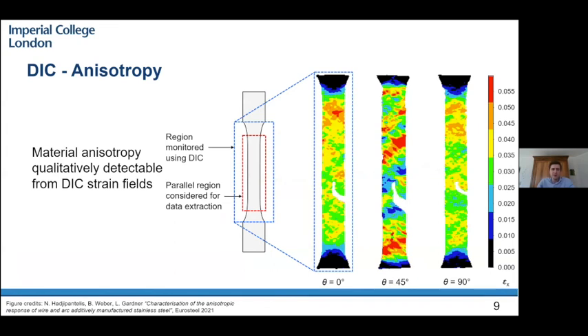From the raw data from these tests, which you can see, for example, on the right-hand side for longitudinal strain graphs, we can also already get a qualitative assessment of the material behavior. And you can clearly see that the strain plots are not the same for the 3 directions. And there's a clear 45-degree inclined strain field, for example, in the 45-degree coupon. So this already gives us an indication that the material doesn't behave in an isotropic way anymore.